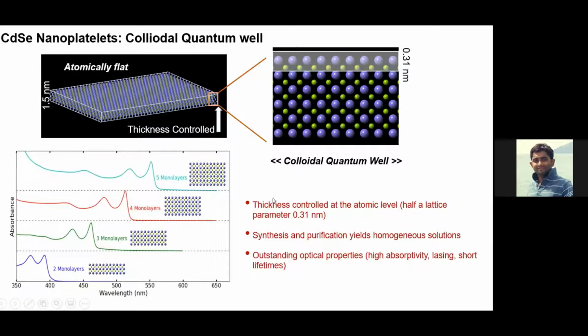As I told you, thickness can be controlled by half of the lattice parameter, like 0.31, half of one monolayer. Interestingly, in the solution technique you can change the thickness of the quantum well. We can synthesize 2 monolayer, 3, 4, and 5 monolayer, and nowadays also 7, 8 monolayer. Interestingly, there is no mixture of platelets, like 4 and 3 monolayer. This is the beauty of chemical synthesis. If you control your synthesis by temperature, by ligand, by solution, you will have only a single type of platelet. And one thing: it has higher optical properties than the quantum dots, almost 10 times higher.